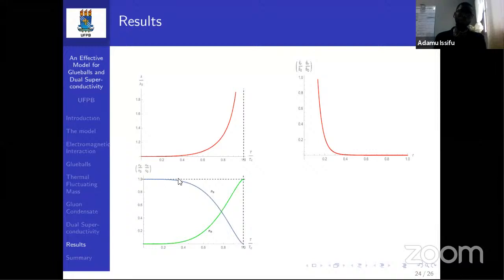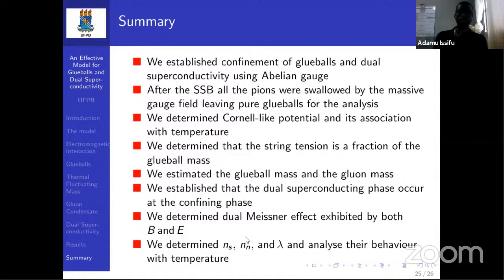And then when you keep increasing the temperature, the normal monopole density starts to dominate the superconducting monopole density. And at the critical temperature, the superconducting material will behave like a normal conductor, because all the superconducting monopoles will vanish, and the superconductivity will be destroyed.